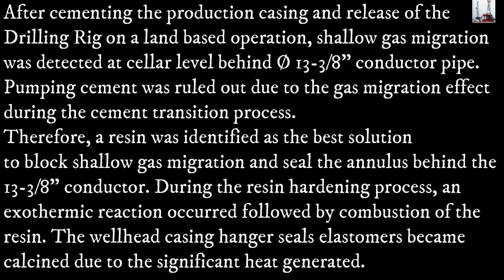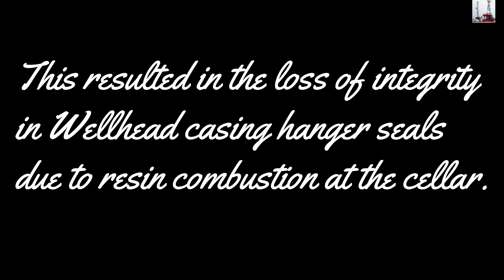During the resin hardening process, an exothermic reaction occurred followed by combustion of the resin. The wellhead casing hanger seal's elastomers became calcined due to the significant heat generated. This resulted in the loss of integrity in wellhead casing hanger seals due to resin combustion at the cellar.